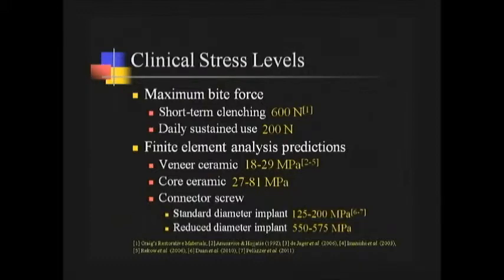Typically the weak point in the implant is the abutment connector screw, and we will see a stress level for a standard diameter implant ranging from 125 to 200 megapascals in the connector screw, and much higher for a reduced diameter implant like we might use in the anterior of the patient. Okay, and so these stress levels are much lower than the strength of the ceramic materials.